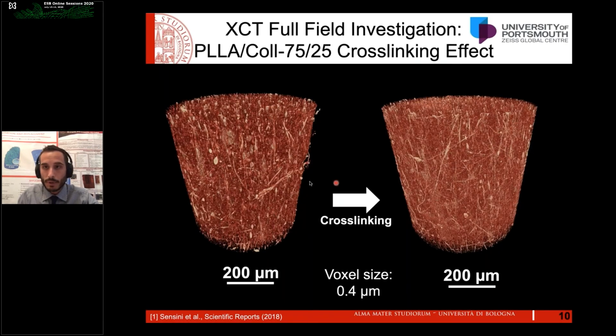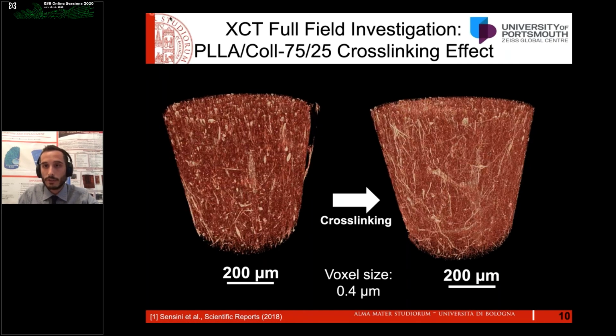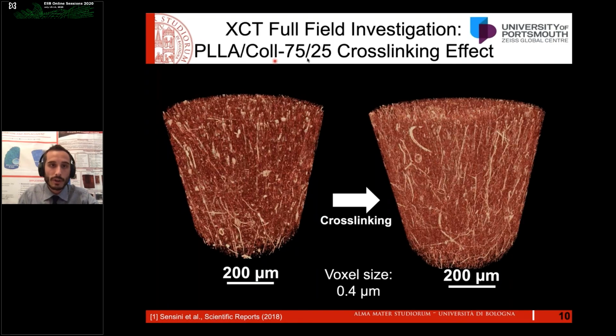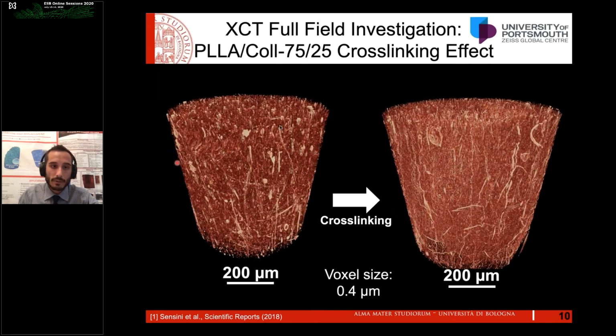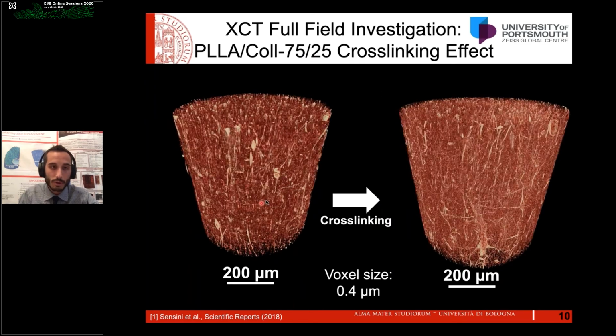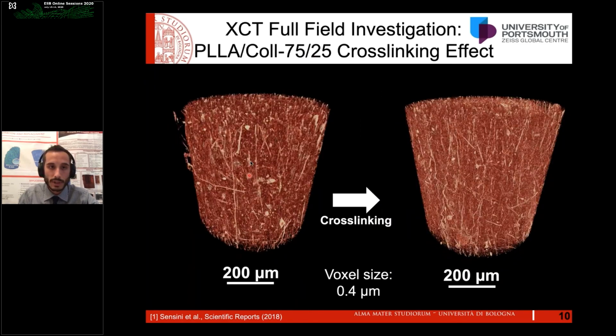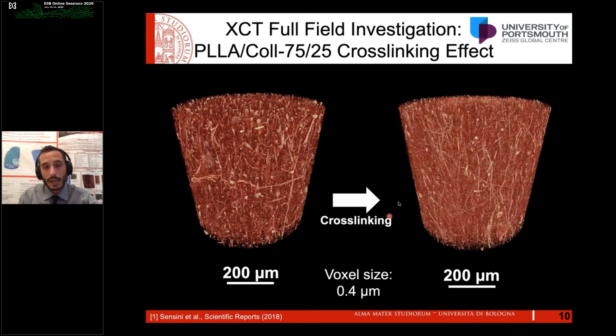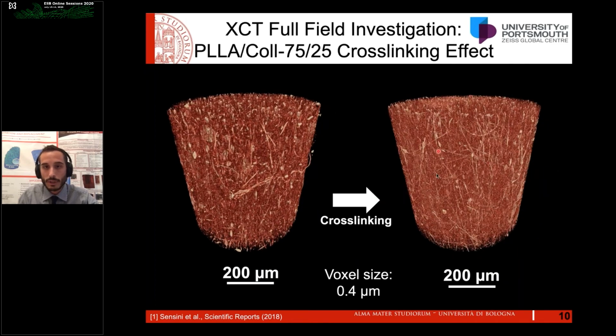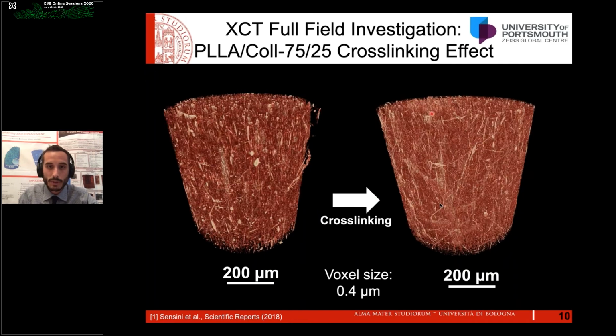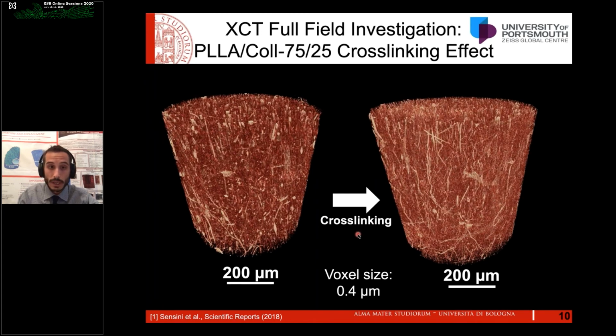Here you can see some videos of the XCT scans for the 75-25 blend. On the left-hand side, before the cross-linking process, you can see the nanofibers that are actually aligned, and after the cross-linking, you can see that the bundles and nanofibers maintain their shape and morphology.